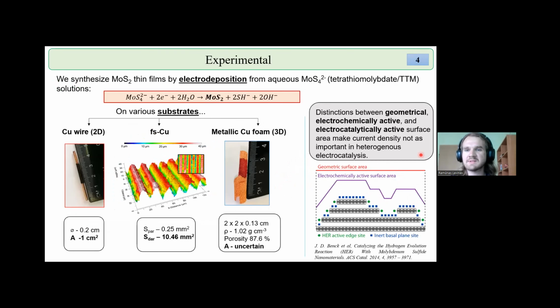So in this study, we synthesize molybdenum sulfide electrochemically. That means that the first part is cathodic deposition, electrodeposition from an aqueous precursor solution. The precursor is tetrathiomolybdate. And the deposition can occur through this reaction. We use various substrates. So we use a simple copper wire, which we consider a 2D surface. And of this surface, we know the geometrical surface area, which is 1 square centimeter.